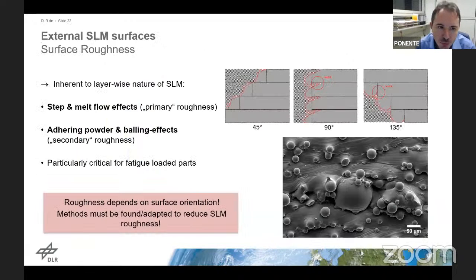Surface quality is very important in terms of the mechanical performance or aerodynamic performance of components. Because if you have crack-like and poor surface, very rough surfaces with notch type of defects due to the process, you have a very poor fatigue performance. That's something you like to avoid. Roughness in the SLM process, however, is something that's intrinsically present because you have this generative step-like process. You see it on the right-hand side. It's a layer by layer process. So this will have an effect that you cannot entirely avoid. It belongs to the SLM process or LPBF process.